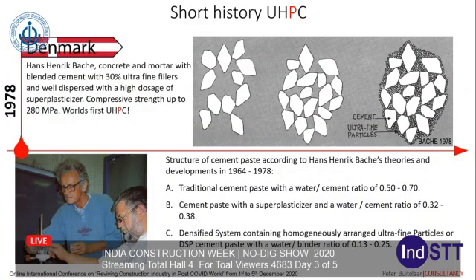Many of the engineers today do believe that ultra-high performance concrete was developed by Lafarge in the early 1990s. Hans-Hendrik Bagge, working as a research engineer for the cement and concrete laboratory at Aalborg Portland, Denmark, was working on high-strength concrete since 1964. Bagge believed that cement particles should be packed much more densely, corresponding to a water-cement ratio of about 0.20. Based on Griffith's classic theory for the tensile strength of brittle materials with a single sharp crack,